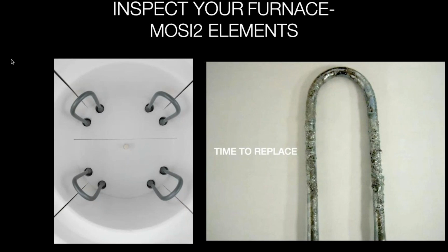Now, if you use a lot of acid early on to cook your work, to color the zirconia, and you didn't burn those out in a light cycle, the fumes would eat up that glass, because hydrochloric acid dissolves glass, etches it. And so once these elements become like this, there's no way they're going to work properly. Now, sometimes you'll see little tiny green contamination that falls on the zirconia beads or whatever pad you're firing it on. And sometimes on the work itself, you'll see little green dots. That's not the element molybdenum. That doesn't leave any color. But it's the glass. So the natural color of silica is greenish.